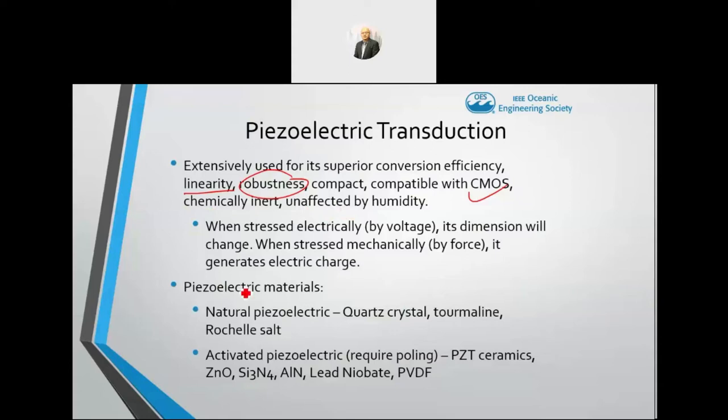For piezoelectric materials, we always have two options: either a natural piezoelectric or an activated piezoelectric. Personally, I'm very happy to use activated piezoelectric material, even though it is a little bit more expensive compared to a natural piezoelectric such as quartz, tourmaline, or Rochelle salt. Even though it requires a high voltage poling process, it carries way higher piezoelectricity compared to natural piezoelectric materials.